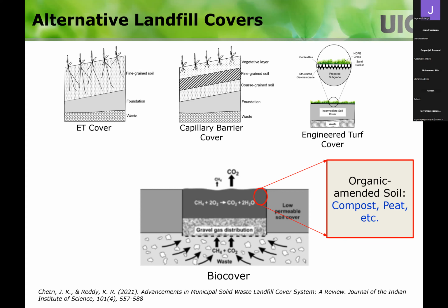And what happens is, with that situation, you have some kind of bacteria, microbes, mainly methanotrophs, that oxidize the methane into CO2. So instead of methane coming out, methane gets converted into CO2, and CO2 comes out. CO2 has less global warming potential, like a 1, whereas methane is 28 times. So if you convert 1 methane, that means you are reducing 28 CO2s. So that's the whole purpose of this one. So you could have low permeable layers outside. These are called windows, or you could have an entire layer as this material. So the whole idea is methane and CO2 are coming into this layer, and in this one, microbially, you are oxidizing the methane into CO2, and then CO2 is coming out.